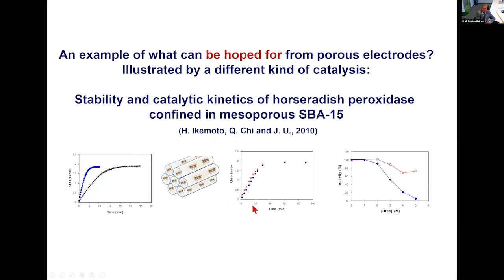If you confine the enzyme in the nanoporous material, you can heat it to 70 degrees and cool it again and you see exactly the same. So it is obviously stabilized in nanoporous or mesoporous material. You can also try to destabilize it by adding denaturing agents, urea. If you have no confinement, here you can go up to maybe 1 mole per liter. If you have confinement, then you can go up to significantly higher concentrations.